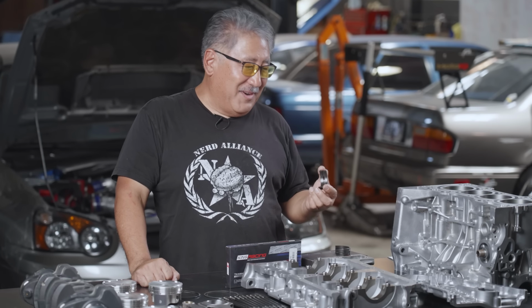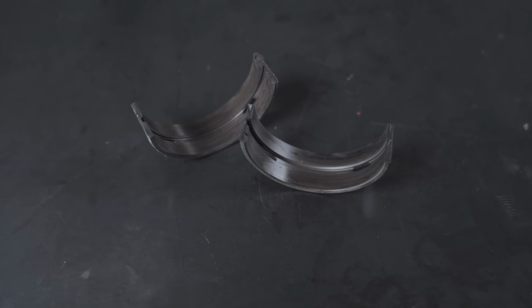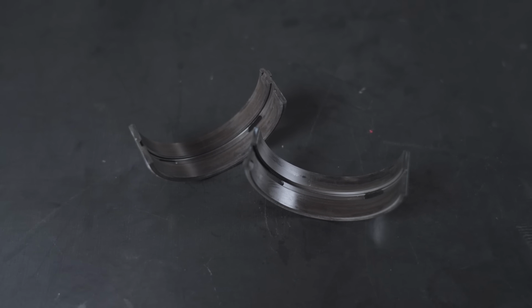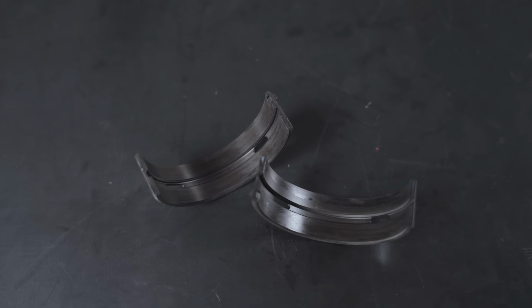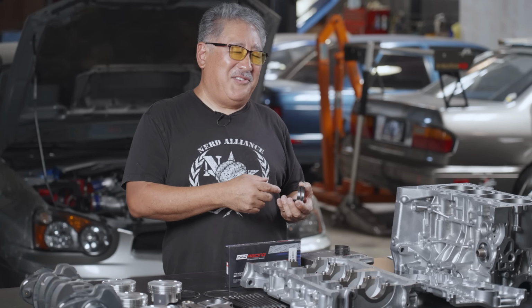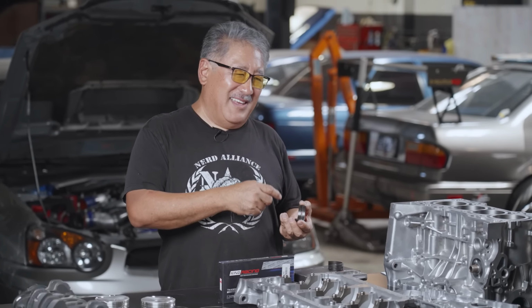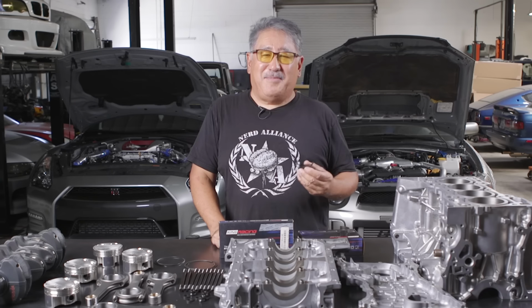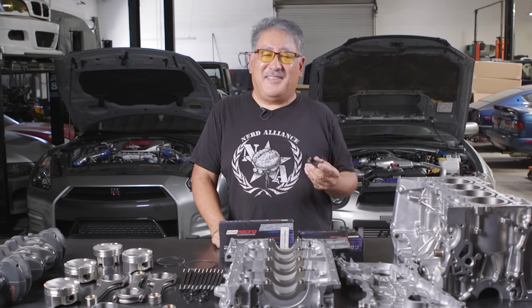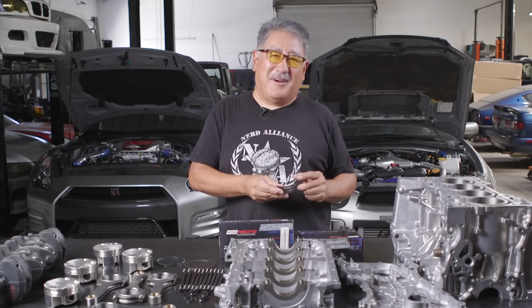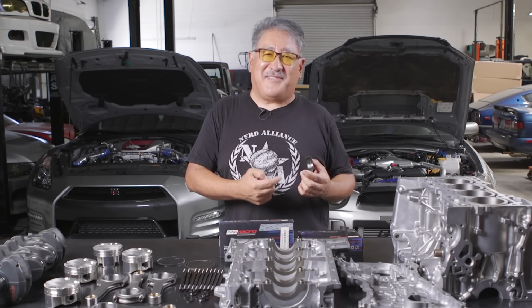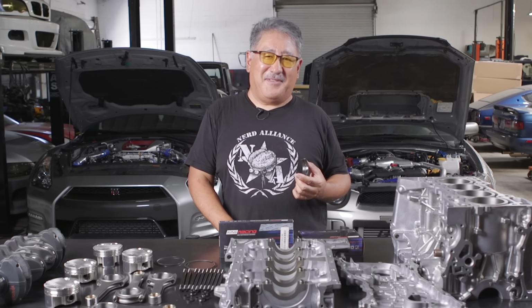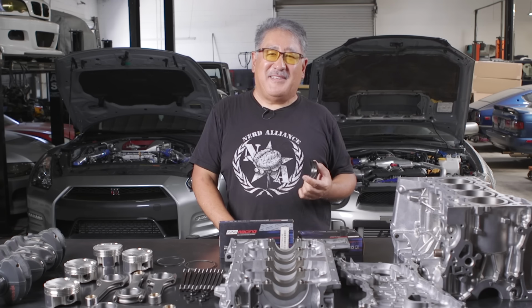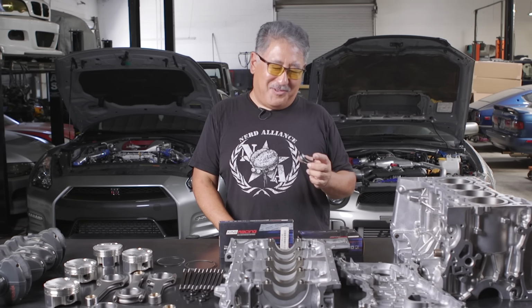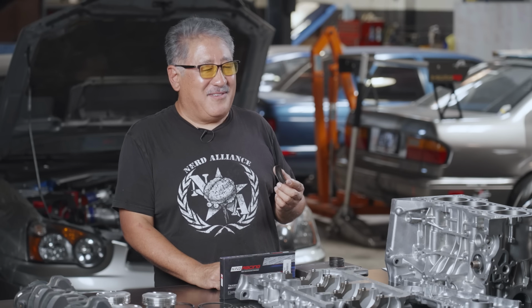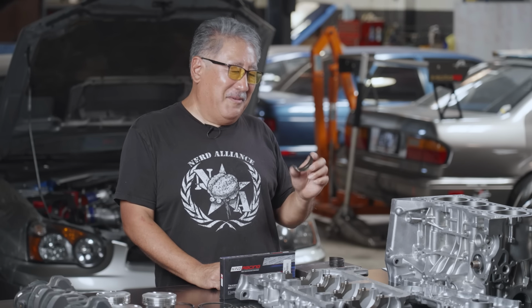The other thing about the King bearing that's cool is it has a black top coat. Now, coated bearings are not a new thing. They're usually there to provide some lubricity. If any part of the crank touches down during operation, it prevents the crank from getting into the softer lead overlay. The big thing about the King coating is that it has a 5% content of copper nanoparticles. These copper nanoparticles make it so the coating actually increases the load bearing capacity. Usually coatings don't do anything for that. So the coating gives you about another 12% more load bearing capacity. That's a King innovation that works really well. We've had incredible luck with King bearings. We've run racing motors for a whole season, take them apart, and the bearings hardly look worn.